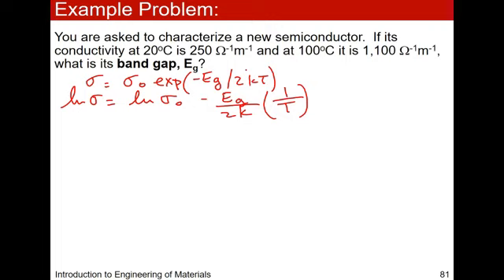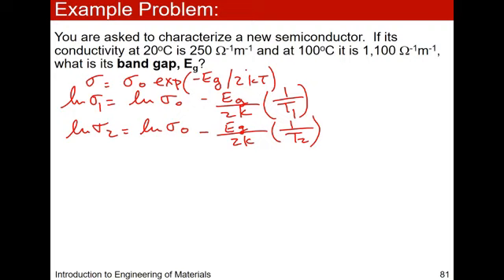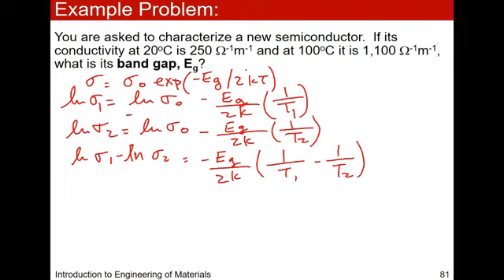Okay, well, analytically, we know that we have a log of conductivity at temperature 1. Bandgap doesn't change, temperature 1. So that's the analytical form. And we know at some temperature 2, we can write out the same relationship, right? So if we want to know what Eg is, we can do what we've done with diffusion and getting the slope of the diffusivity plot. We can get the activation energy, aka now the band gap, in the same way, right? We can say, okay, well, we take this minus this gets you 0. So we can say, okay, well, if we subtract equation 2 from equation 1, we get something that looks like that.